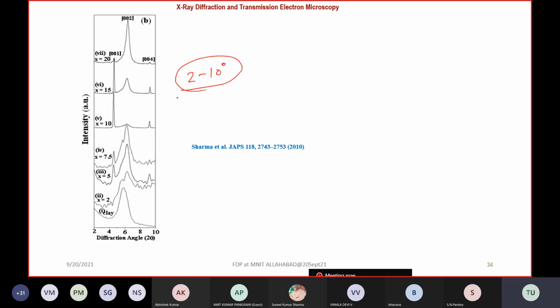In montmorillonite clay, 3 planes are very important: 001, 002, and 004. Just see, this is pure clay, this is pure modified clay. Then 2 weight%, 5 weight%, 7.5 weight%, 10 weight%, 15 and 20 weight% of modified clay have been added in the polymer nanocomposite. Here you are getting a peak, but it is lost due to noise. But at 5%, you are going to get the peak. Similarly, at 7.5% you are getting the peak.